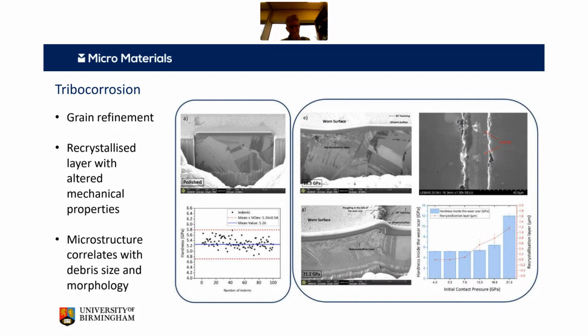And after the wear tests, so after the tribological tests, they've then sectioned through that, and you can see that the microstructure that you see on the left has now evolved into a much finer microstructure just under the surface. So you're having this recrystallized layer, a tribologically transformed structure, if you like, and this has altered mechanical properties. And as you can see bottom right there, a different group in Birmingham has been looking at how that changes in terms of contact pressure and layer thickness. This was interesting because they found some neat work showing how this microstructure correlates with the size and morphology of the debris. That is one of the issues in these systems, is how this evolves.